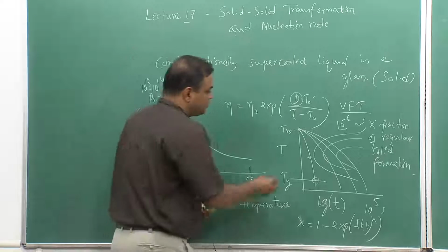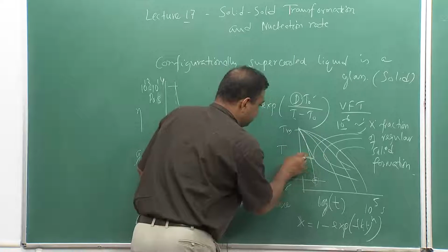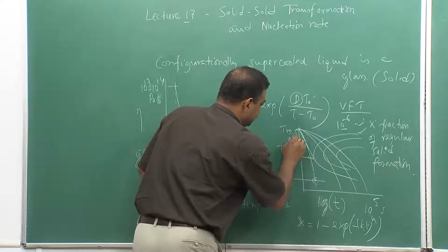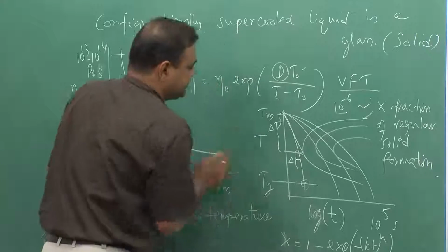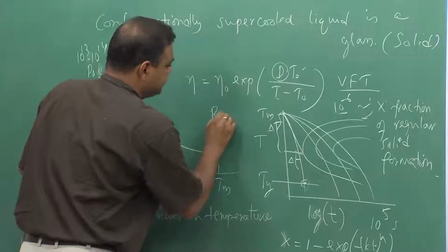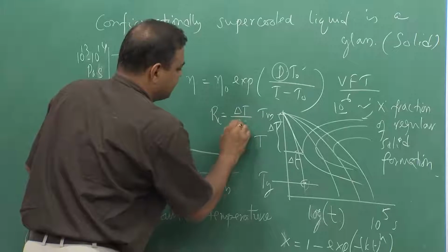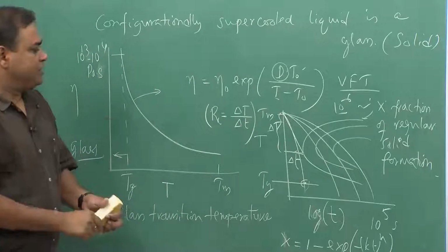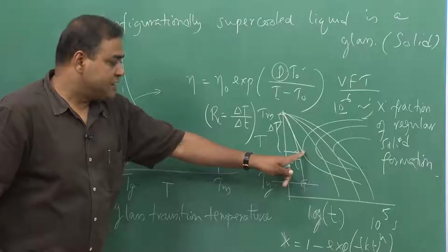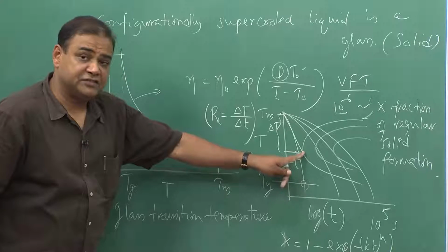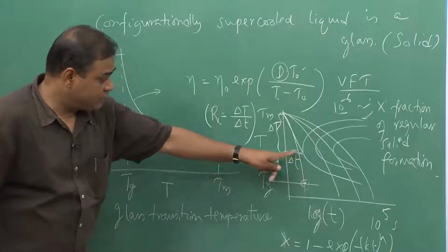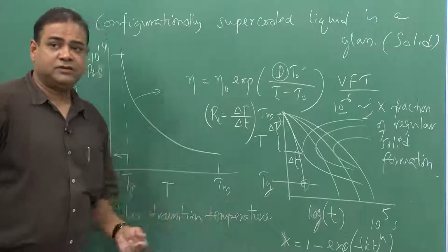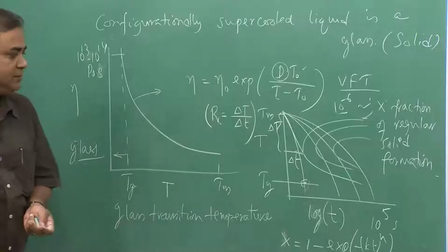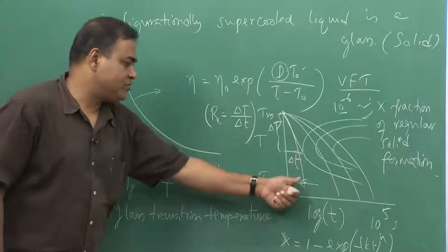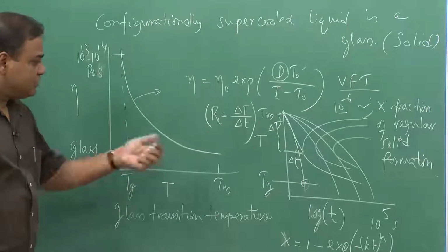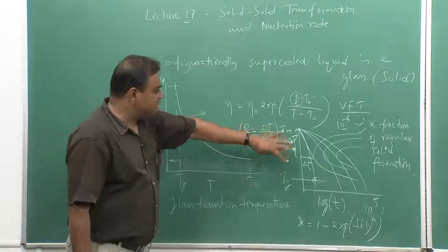That means the critical cooling rate is this one, where this is my del T and this is my del T. So the critical RC, which is the critical cooling rate, is measured in this form. A cooling rate greater than this, that means if we go towards the left, the liquid would remain as liquid. So at that time I can take the liquid to the glass forming temperature, and then it will form glass. So this information will be